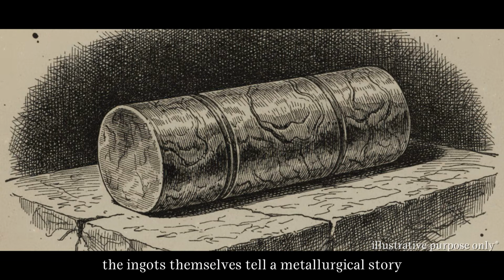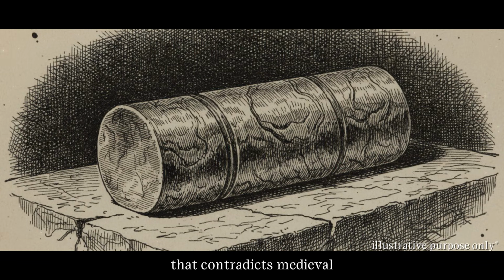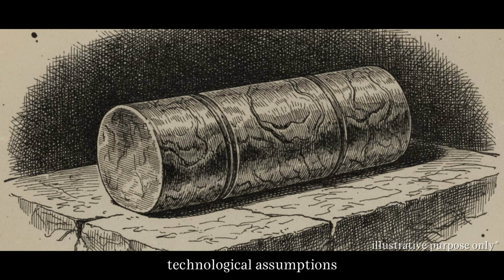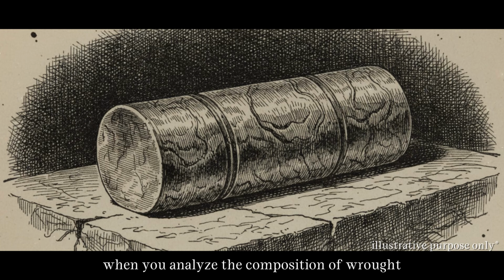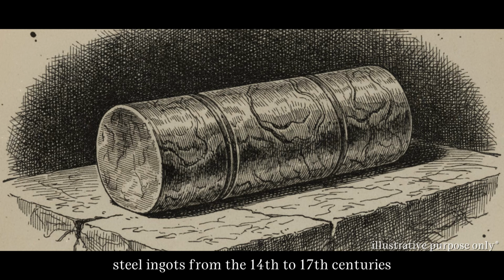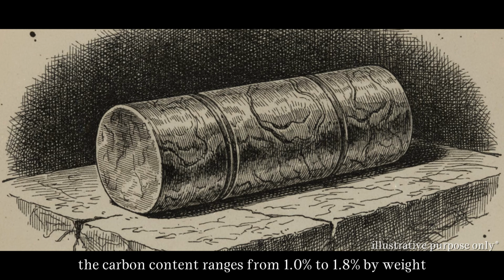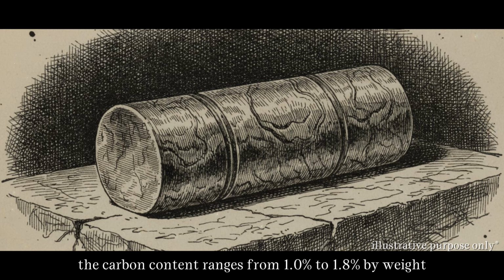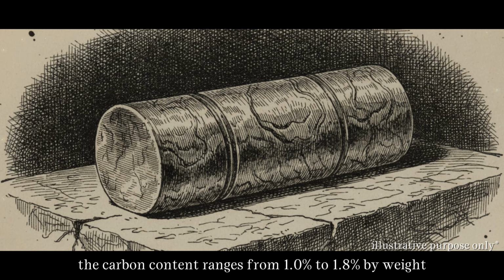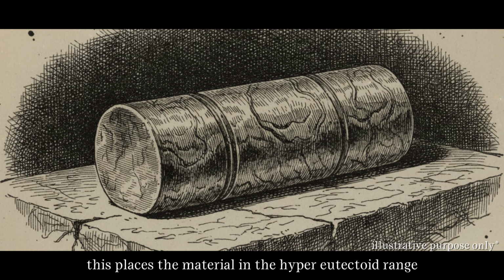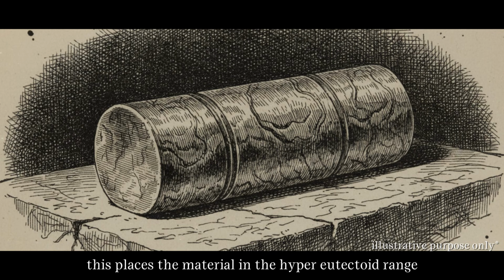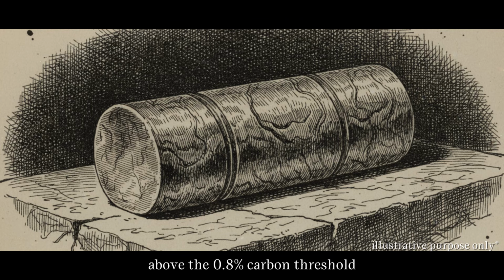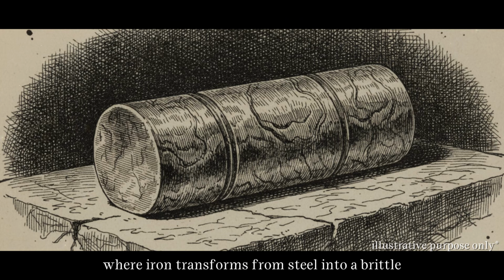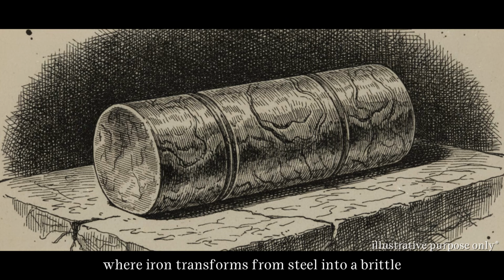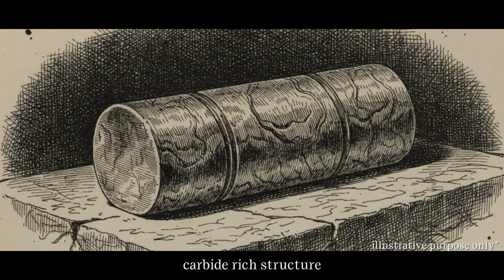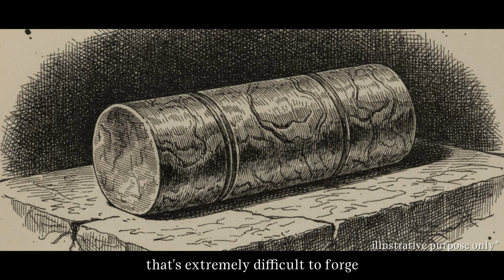The ingots themselves tell a metallurgical story that contradicts medieval technological assumptions. When you analyze the composition of wootz steel ingots from the 14th to 17th centuries, the carbon content ranges from 1.0% to 1.8% by weight. This places the material in the hypereutectoid range, above the 0.8% carbon threshold, where iron transforms from steel into a brittle, carbide-rich structure that's extremely difficult to forge.